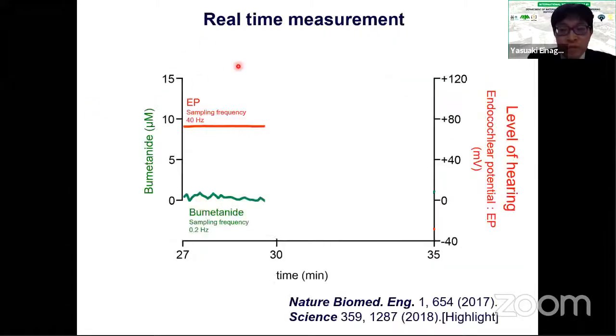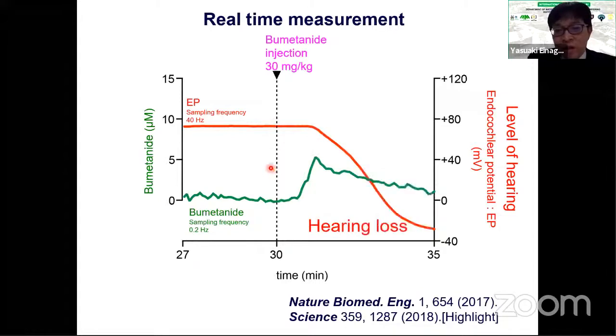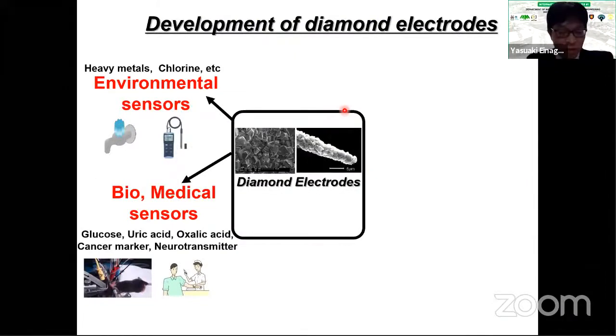So this is the result of the real-time measurement. As you can see, before injection, the bumetanide concentration is 0 like this. On the other hand, the hearing ability is very good, plus 80 millivolts is normal. And here, the bumetanide drug is injected. Then 1 minute later, the drug comes to the ear. As the bumetanide comes into the ear, at the same time, the hearing ability decreases. This kind of relationship between function and concentration is observed directly in real time. This is an example. Okay, I have 10 more minutes, okay?